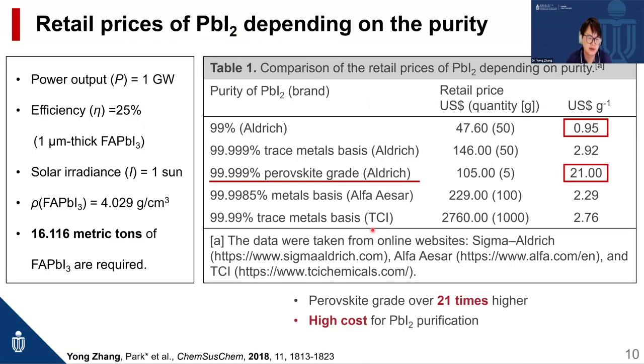Actually, this idea came out when I was a PhD student at SKKU. At that time, we found that perovskite grade lead iodide at 99.999% purity is priced even 21 times higher than low grade 99% lead iodide.